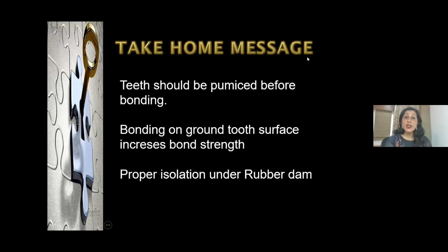And this is really interesting because I have seen many people not even touching the surface and going ahead with the bonding and composite procedures. Your restoration will fail after some time because composites give best results when they are bonded on ground tooth surface. At least roughen the surface before doing your restoration. And if the whole restoration is in enamel only, then total etch techniques work really well. You need not grind the surface, or with self-etch also you can achieve your target. But whenever your preparation is in dentine, remember always to roughen or grind the tooth surface.